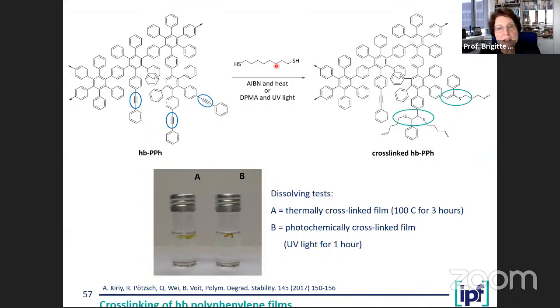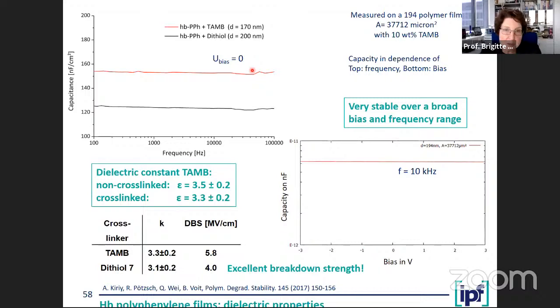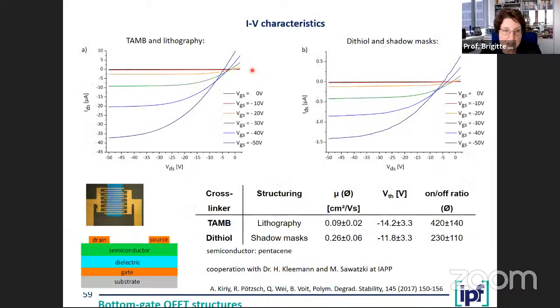And we also did another click type of chemistry, which is the addition of thiols to this triple bond. It works also really very well. It shows good performance, perfect dielectric layers, very, very stable over high frequency and a high bias range. And it works, of course, also in the OFET.